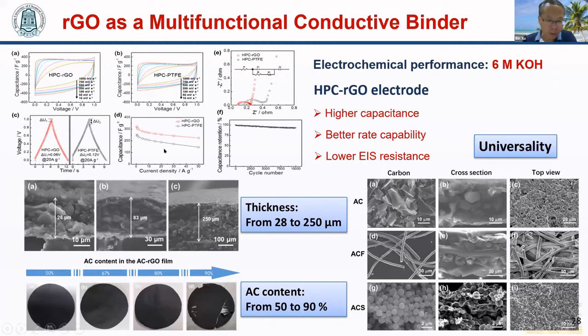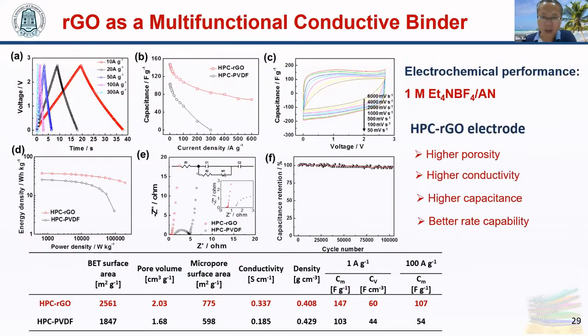The thickness is controllable from 28 to 250 micrometers, so it can meet the requirements of different supercapacitor designs. And the carbon quantity is also controllable from 50 to 90%. Most importantly, this method is universal. With this method, we fabricated powdery carbon, fibrous carbon, and spherical carbon into freestanding flexible films with better performance than conventional PTFE bonded electrodes. Being measured in non-aqueous electrolyte, the advantages of the rGO bonded electrode are highlighted.